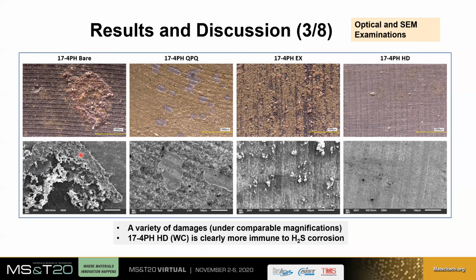Here I have the reference material. I have the nitrided 17-4 by the QPQ process. I have another nitrided surface, and I have the tungsten carbide produced by the CVD process. So obviously we have a variety of damages as we look from left to right. It seems the least damage is on the right here. We still have a bit of discoloration as we see elsewhere. This discoloration is to a lesser extent, and when we look in the SEM, we don't see much happening.